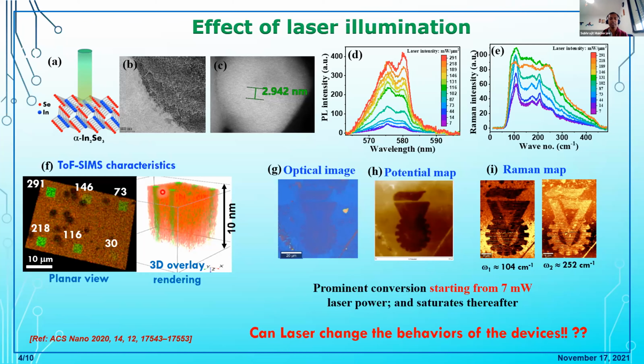We also did the cross-section characterization to see how far we can change the property of this. The green lines are actually the indium oxide and red is indium selenide. So it is possible to change the whole film thickness by using laser irradiation by choosing optimized conditions. This can also change the surface potential, which is related to the electric property of the devices. So these are the optical image, corresponding surface potential and Raman map.